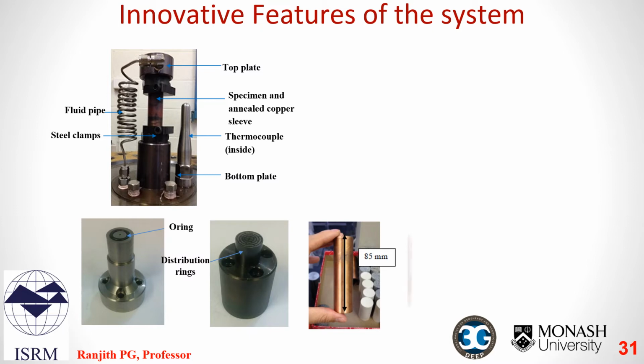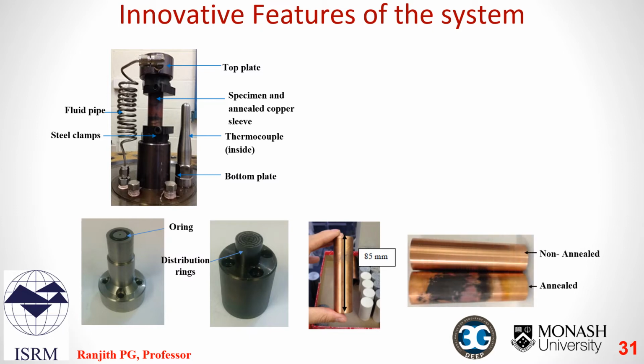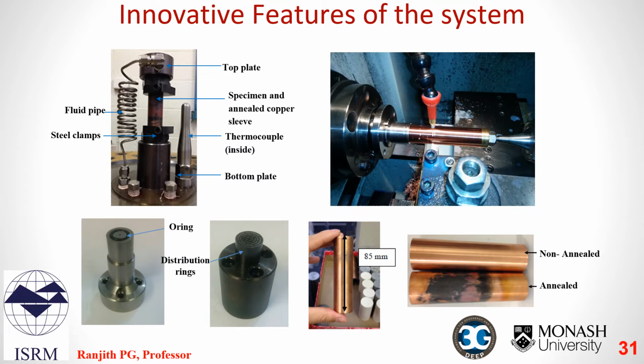You can also see the specimen covered with an annealed copper sleeve. We are talking about above 200 degrees C and extreme confinement and injection pressures, so we cannot use available latex or Teflon membranes. Our innovative solution is a custom-made copper sleeve. We annealed it with an oxyacetylene flame and water quenched it to make it extremely soft and ductile.